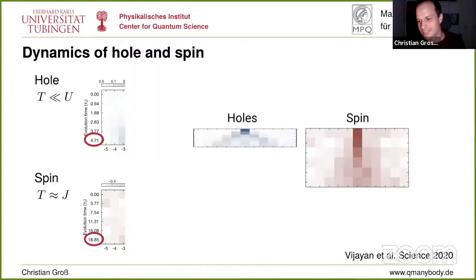I can also show you that scaled, basically by squeezing these 2 plots. And you see the hole has already reached basically the edge of the system, while the spin, well, has not even noticed that there was a hole shot into the system, right? So there's really a very strong separation of timescales here.